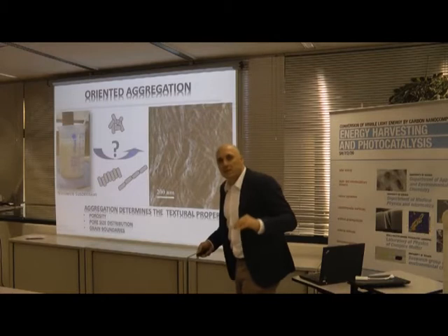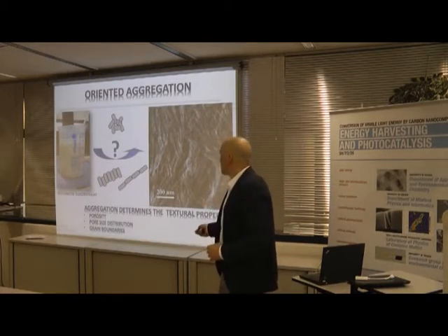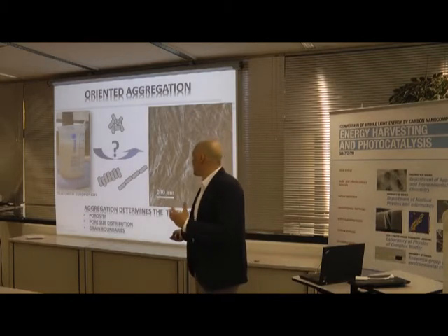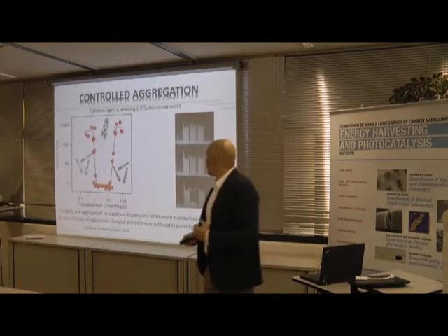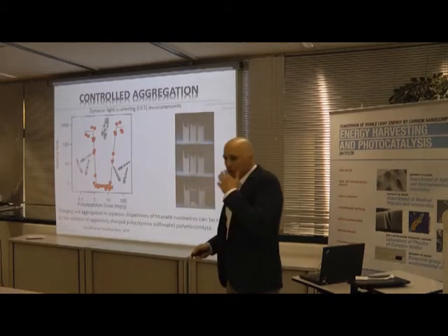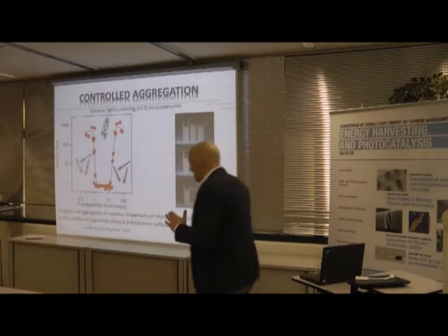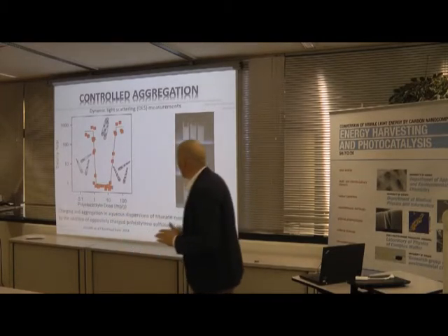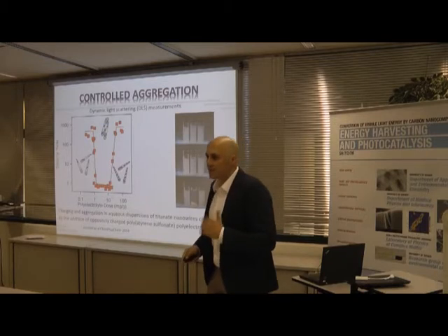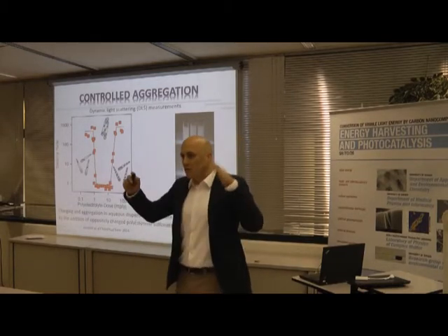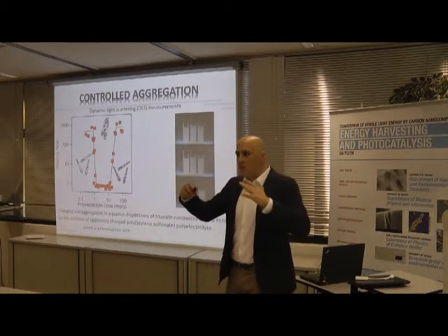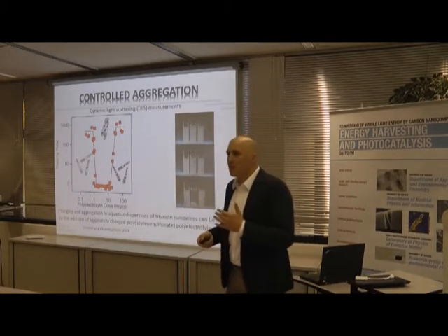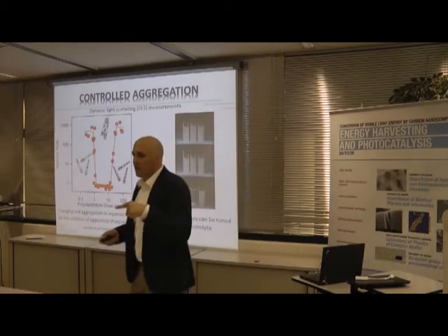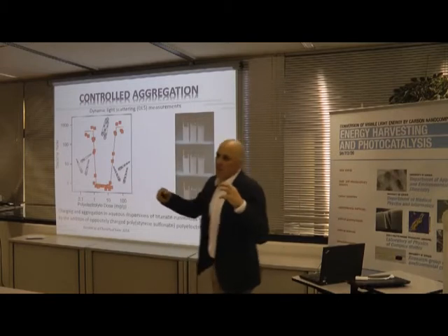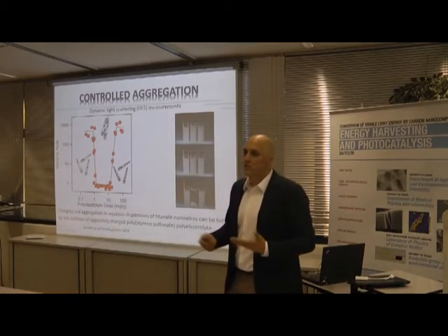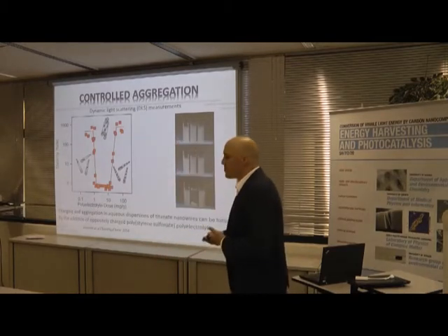So we studied in more detail the aggregation of this system, because the aggregation will determine the porosity of your film, the pore size distribution, and the grain boundaries. We've seen that they had a really important effect. Teamed up with a specialist in Geneva, we studied from A to Z all the aggregation properties of this system in liquids. This is also very important if you want to do photocatalysis in liquid suspensions. When you want to separate the nanoparticles from your sludge, that's a very crucial problem from the practicability point of view. Because if you deal with nanomaterials, you don't want to discharge them into the environment. So you need to separate them.